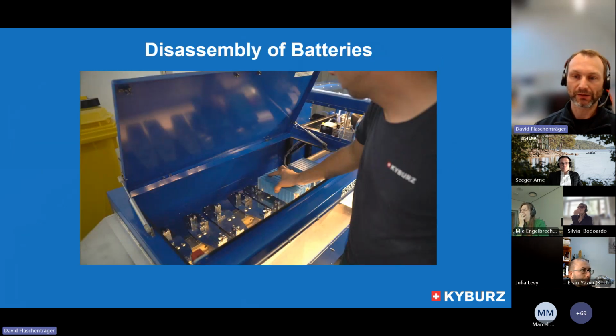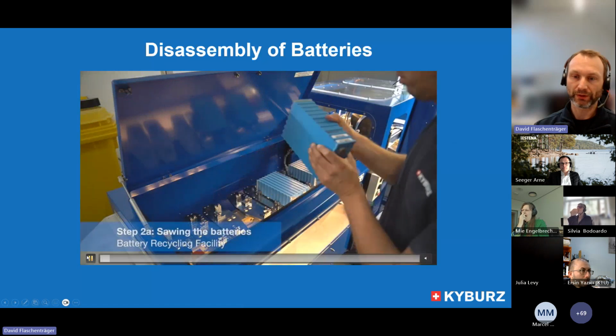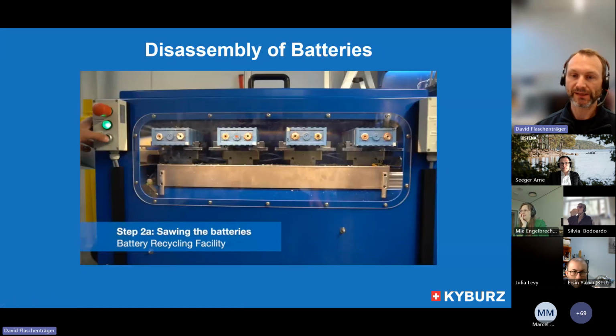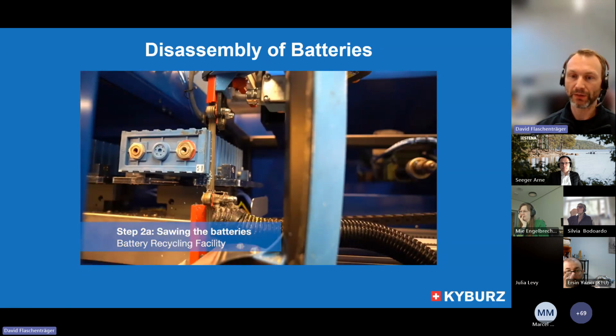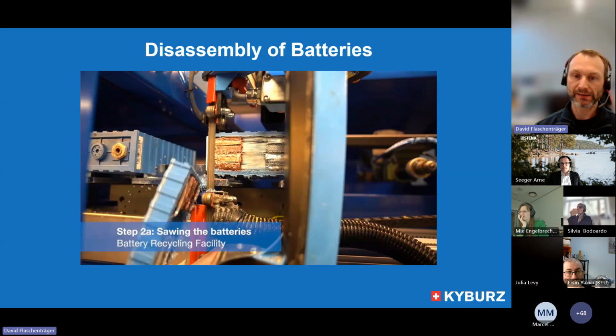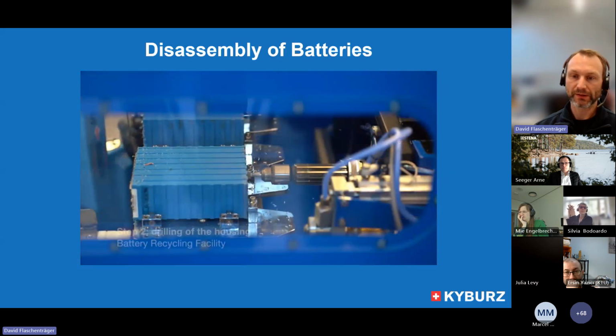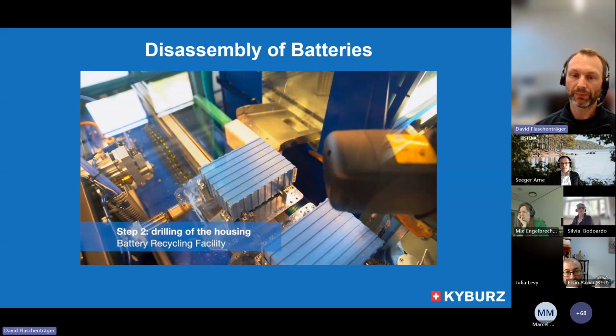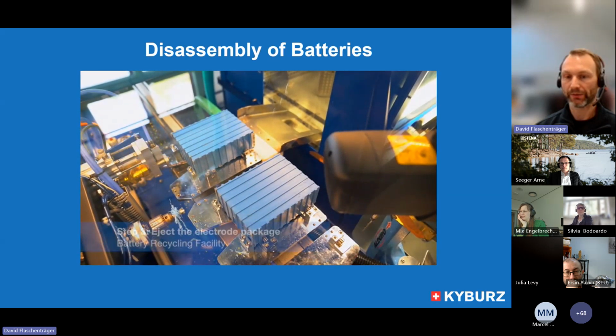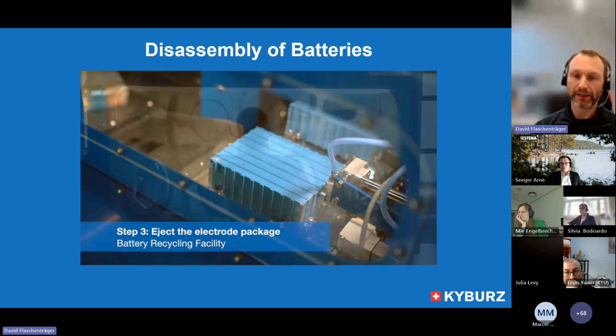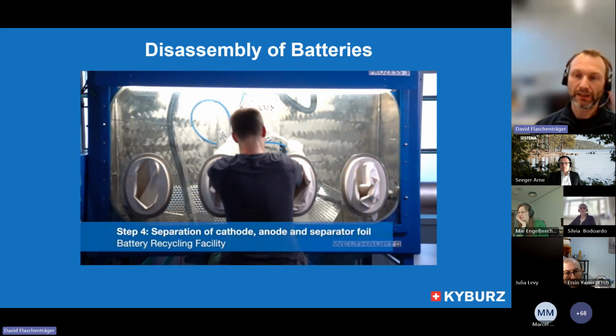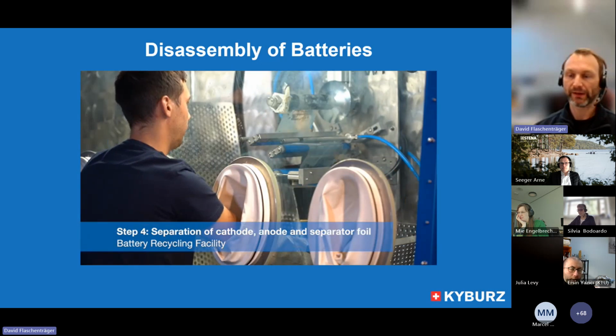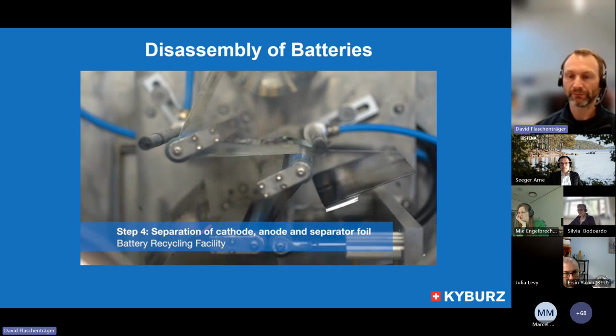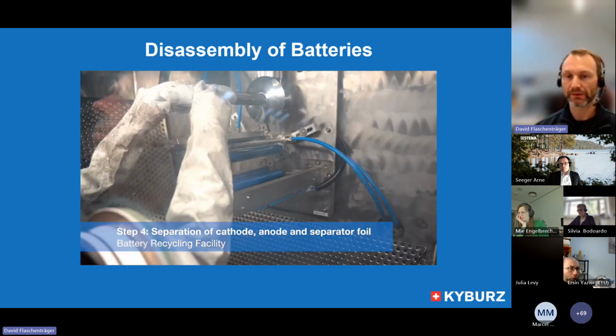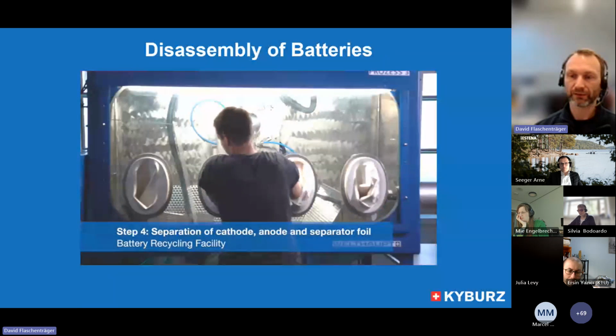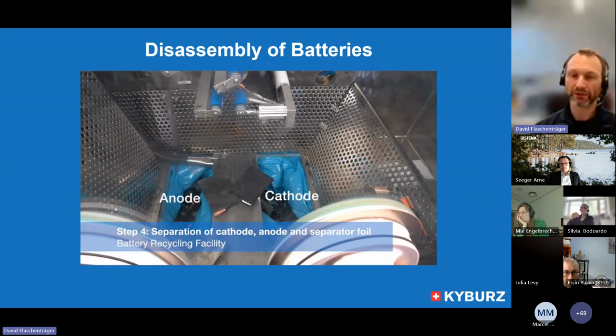And I would like to show how the process looks with a brief video. Some of you might already know it. That's the facility which is literally standing 20 meters behind me. So first, the cells that mostly stem from our vehicles are opened by a traditional sawing process. And then by using compressed air, we eject the electrode pack out of the casing of the cells. In the next step, which is partially manual, we start separating anodes from cathodes. So we get anodes in one bin and cathodes in a different bin. And we never mix these materials. That's very important because in this way we can assure a very high material quality with almost no contaminations.